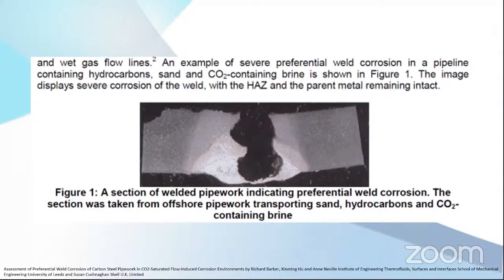and you can see that the parent material is attacked very little, but the weldment is attacked very fast. This is called galvanic action. So this is anodic, this is cathodic. So the small anode has to protect all the cathodic sides. So this has accelerated corrosion.